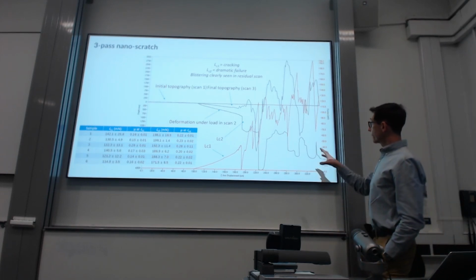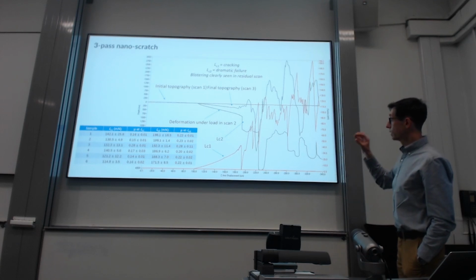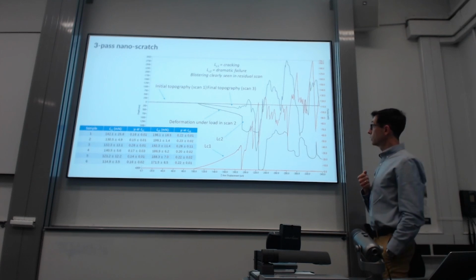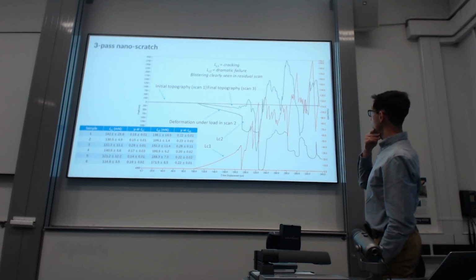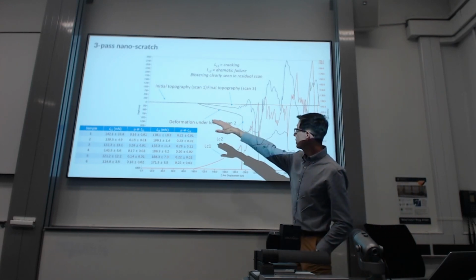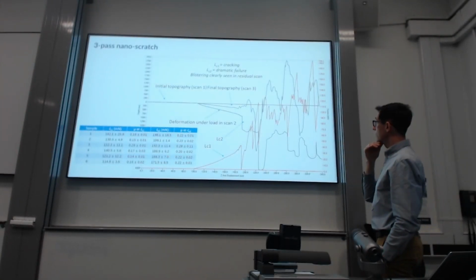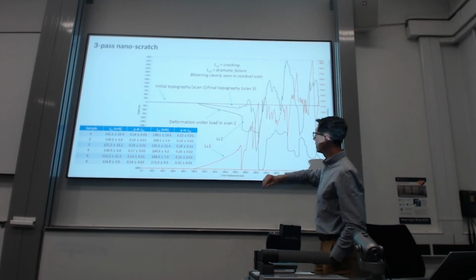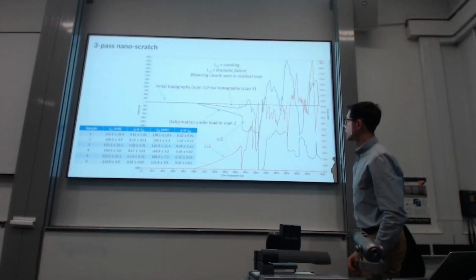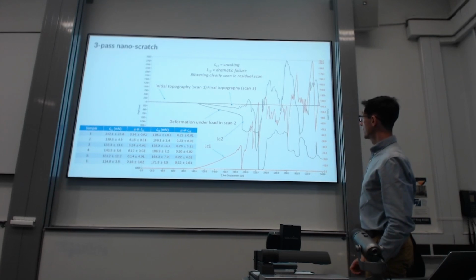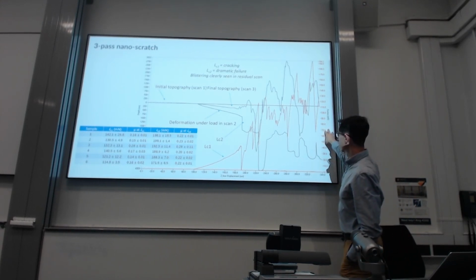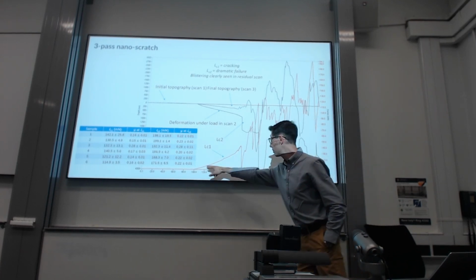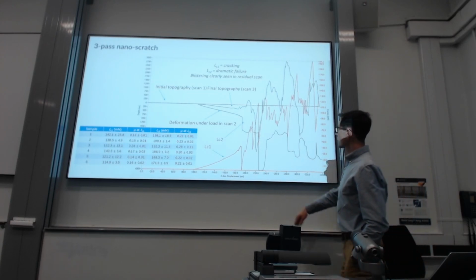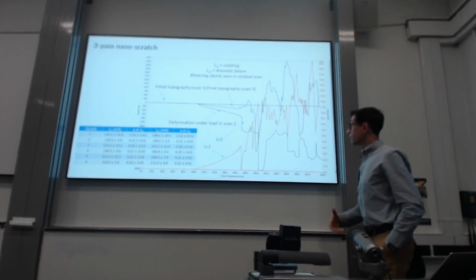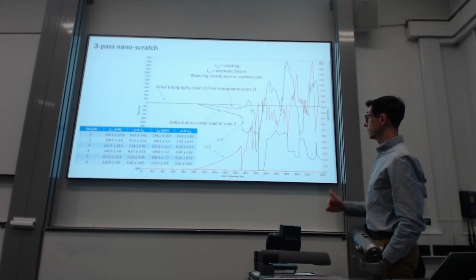So, looking at the output of the 3-pass nano scratch experiment, you can start looking at some critical loads in this type of test. Just to explain what's happening in this graph: the initial topography scan is hovering around 0 there, no damage yet on the sample. Then scan 2 under load is that curve, so we can clearly see the increased evolution of depth as a function of applied load, and we can also look at the friction behavior during that load ramping event, which is your red curve there. And then the third scan is here in the middle, so the residual deformation damage, which you can measure with that low load third scan.